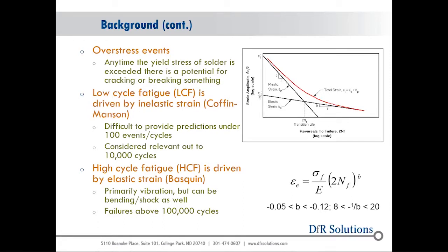So low cycle fatigue of the metals usually is going to be the Coffin-Manson equation. And really we're looking at events that occur 100 to 10,000 cycles. Once you get below 100, it really gets very difficult to predict very low cycles of failure if it's a bending type of event. So we're using the Coffin-Manson equation, which is an inelastic strain range. And then for high cycle fatigue, we're using a Basquin equation, which could be elastic strain or stress, because those are directly proportional when we're elastic. So we're also looking at things that occur hundreds of thousands of cycles, such as maybe car door slamming, anything that's lower level types of amplitudes.